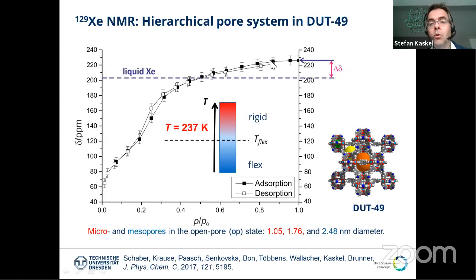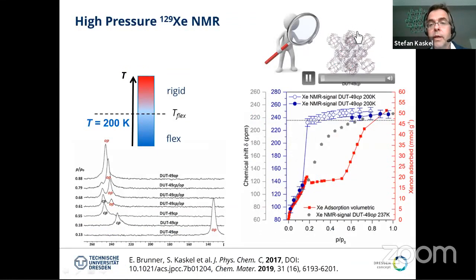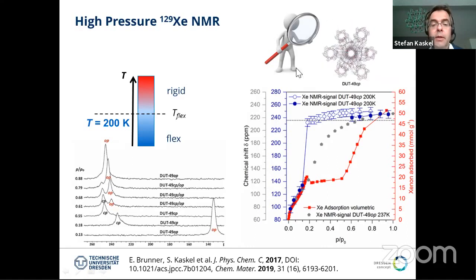But once we approach the highest filling, the chemical shift is very close to the liquid xenon in this case, basically. So of course, due to the surface interaction, there's a deviation. But now comes the interesting point. Once we go below the flexibility temperature, so at the temperature where the system becomes flexible, we can watch with the xenon, basically with the xenon NMR, how the structural transformation takes place.